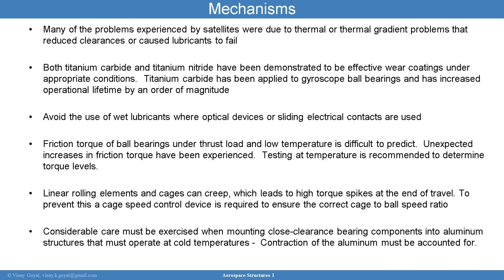We also have the situation that we need to discuss about linear rolling elements and cages, which can creep, which leads to a high torque spike at the end of travel. To prevent this, a cage speed control device is typically required to ensure the correct cage to ball speed ratio.